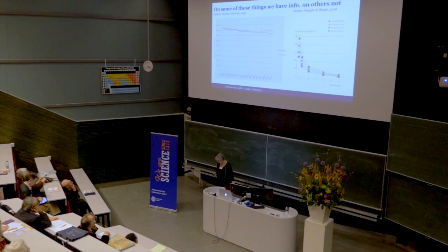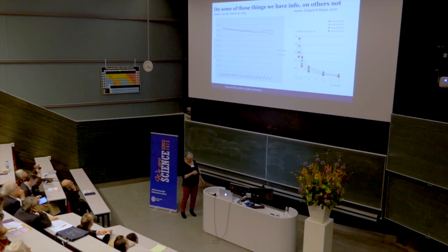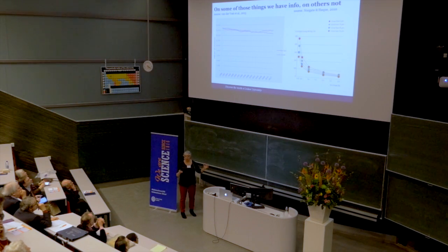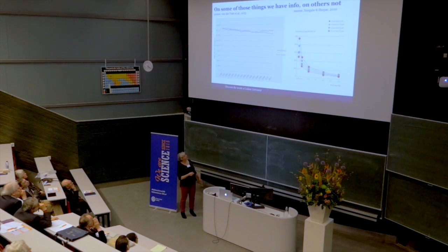The other picture is of the relation between the energy use and ore grades. Here on this axis we have the embodied energy, so the amount of energy throughout the whole production process chain that is needed to produce a kilogram of copper in this case. And here we have the ore grade. So if the ore grade here is an ore grade of 3, if that goes down towards 1, it's now about 0.5, the average ore grade, you see that the amount of energy that you need goes up.